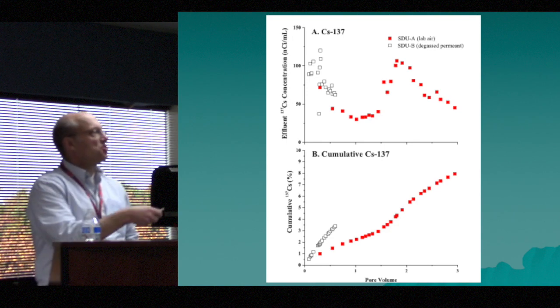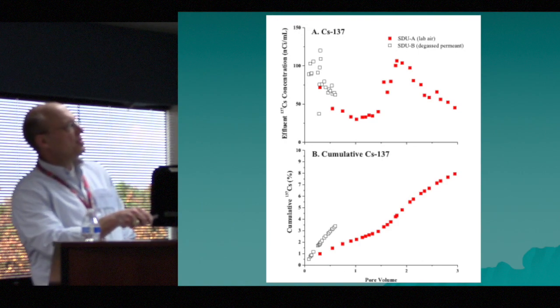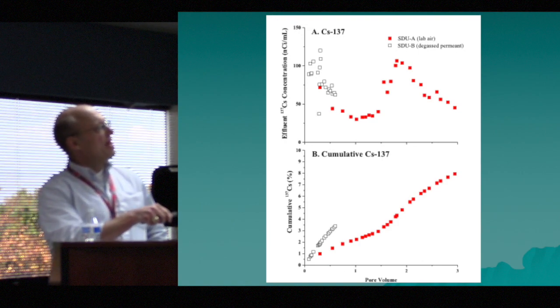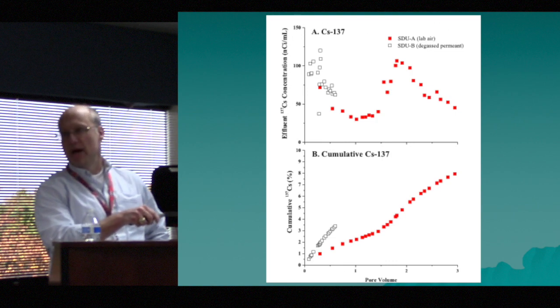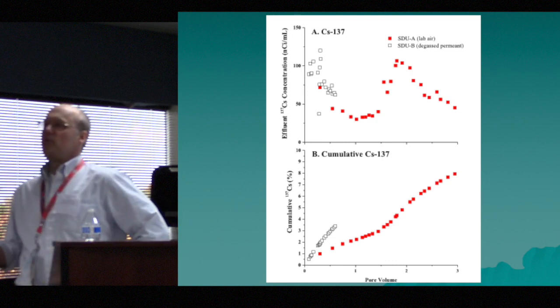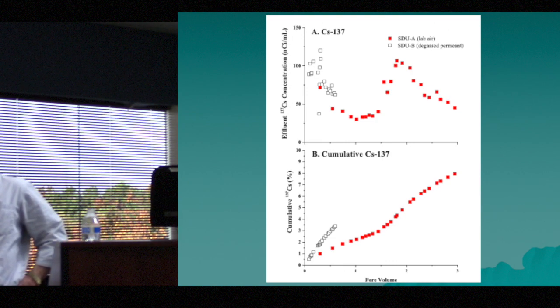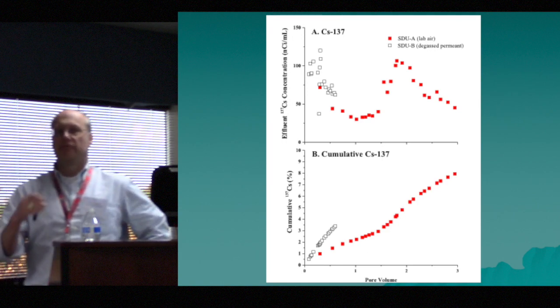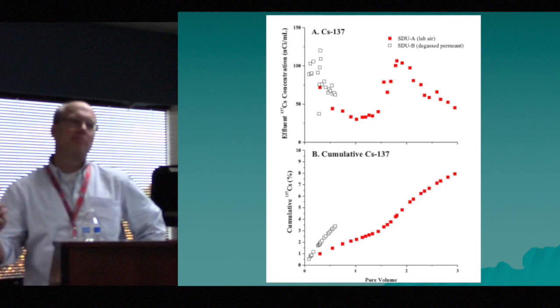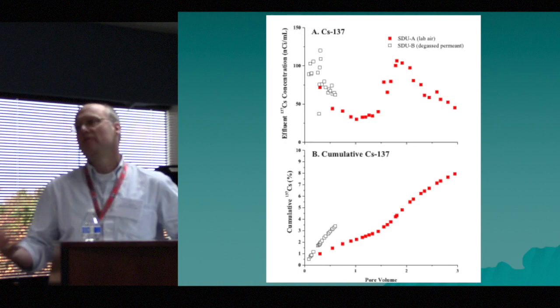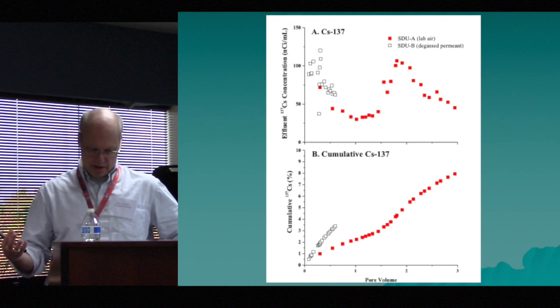But we start to see strange things happening. We see the cesium-137 level go down for a while, and then all of a sudden it comes back up. This coincides with when hydraulic conductivity goes down, the flow rate goes down, and the residence time goes up. So this seems to be clear evidence for some kind of residence time effect going on.